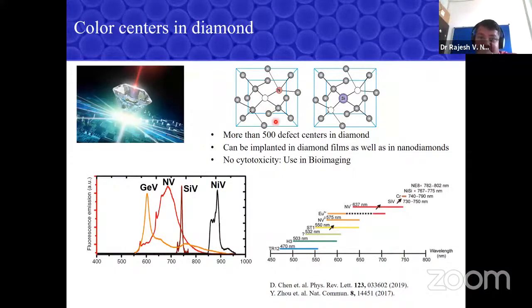And nitrogen is not the only vacancy. You can have many vacancies. You can have chromium, silicon, even tin vacancy. There are many hundreds of vacancies. Depending upon these kinds of defect states, their emission property changes from 450 to 800 nanometer.